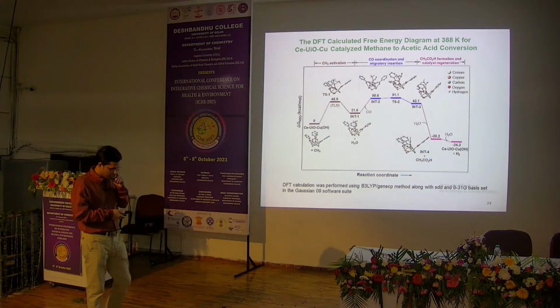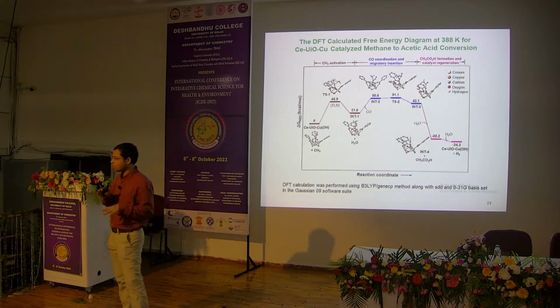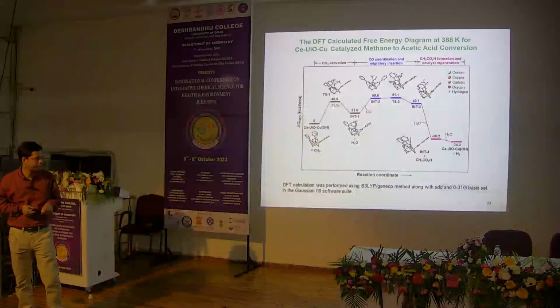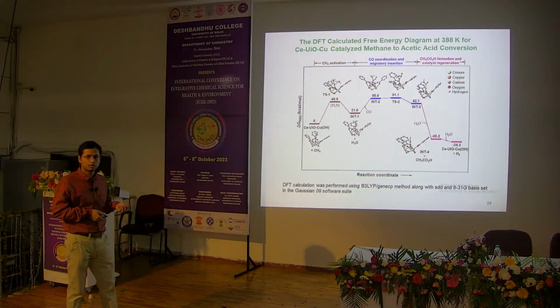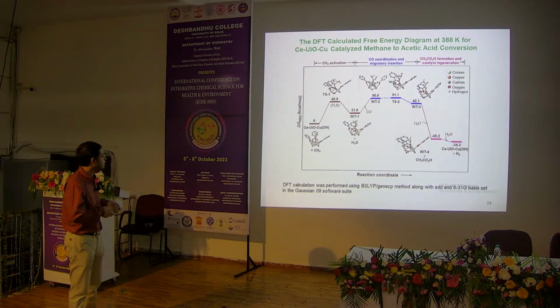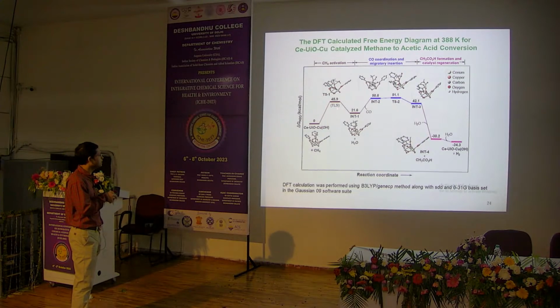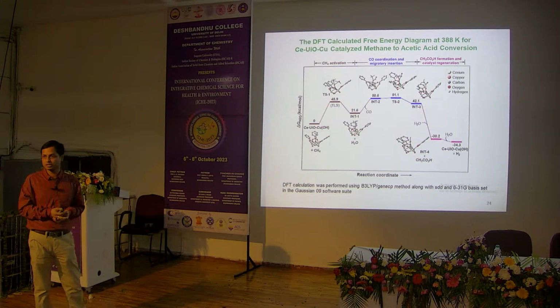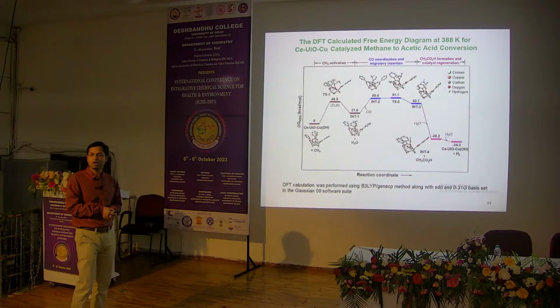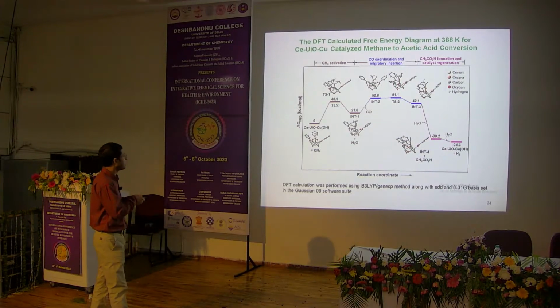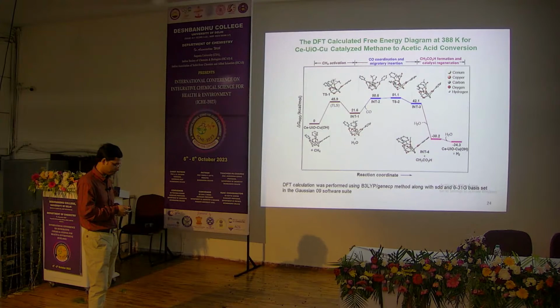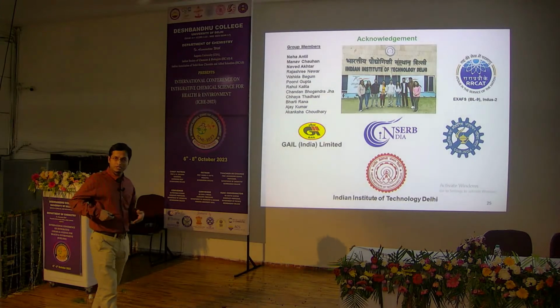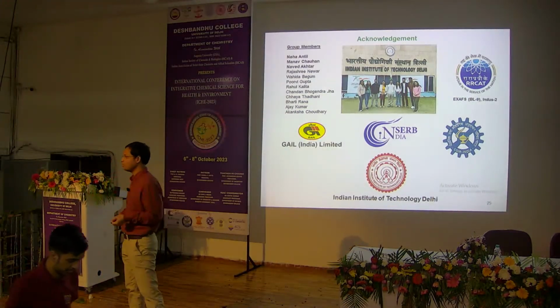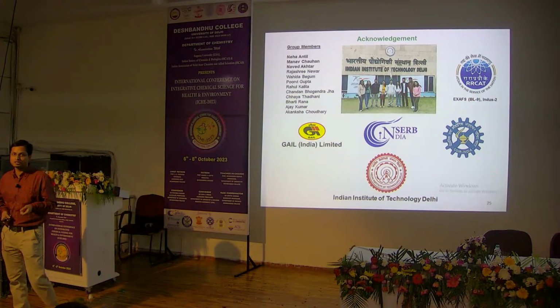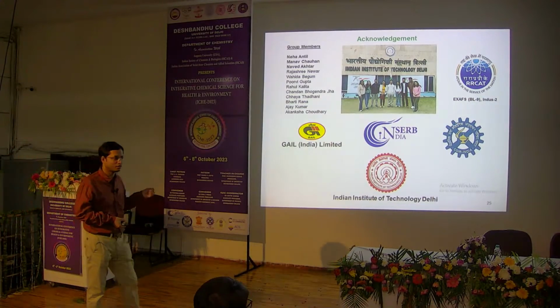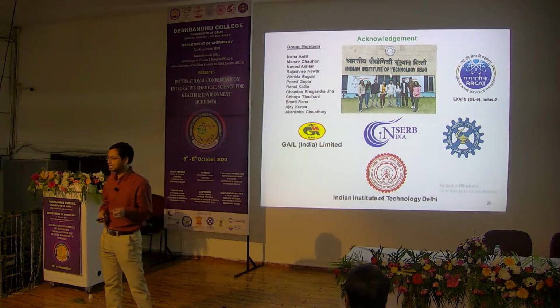we also quantified the hydrogen by GC. We also calculated the whole catalytic cycle by DFT to understand what is the turnover limiting step or rate determining step, and we have found that the first step, that is the sigma bond metathesis between the methane CH bond and the copper hydroxyl groups, has the highest barrier and is the turnover limiting step. So the project is still going on, and we recently have developed another one, an iron catalyst, whose activity is much higher than this catalyst. It is not published yet.